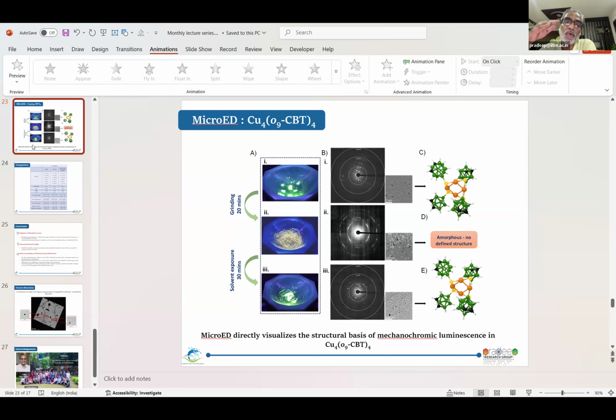For example, a molten crystal is recrystallized, or let us say from a glassy state it is recrystallized. You are getting great translational order by reducing the rotational disorder. So maybe the system has a certain kind of rotational disorder, as you can see in the carborane, where a lot of rotations are possible. Something is happening to the system. Yes, sir, this explanation fits well.